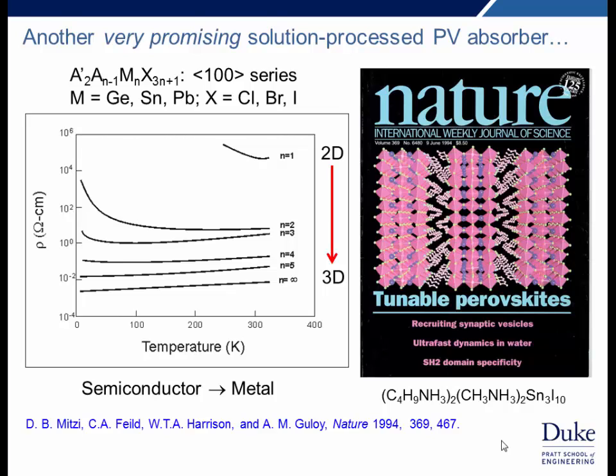And so with that, I'd briefly like to mention the other very promising solution process semiconductor, and these are the perovskites. Our interest in this started back in 1994, where we were looking for solution processable semiconductors, low temperature solution processable semiconductors, and we decided to look at metal halides. Metal halides are usually pretty poor conductors, but this family here, A'2 A(n-1) Mn X(3n+1), where A' is a large organic cation separating the perovskite sheets, A is a small cation within the perovskite sheets, M is, of course, the metal, and X is the halogen. N refers to the number of perovskite sheets between the large organic cations.